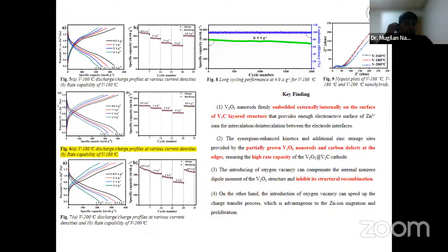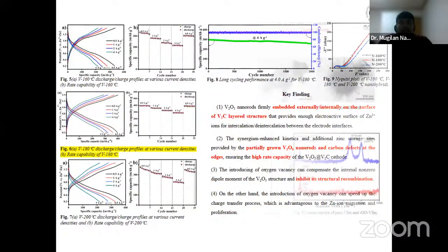On the other hand, the introduction of oxygen vacancy could speed up zinc ion migration and proliferation. And this was the first partially oxidized work, published as an article in Chemical Communications.